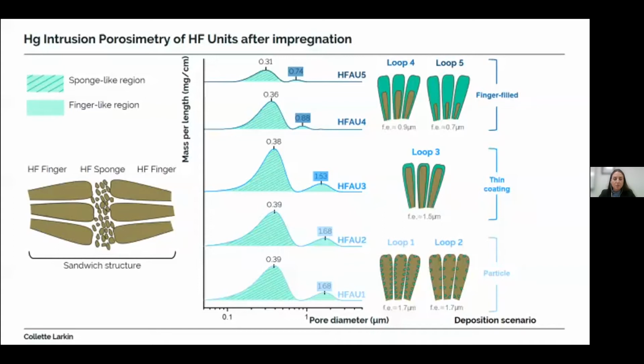And the finger fill deposition scenario effectively builds upon the thin coating scenario, such that once the inner surface area was completely coated, applying additional impregnation loops resulted in calcium oxide depositing onto the existing calcium oxide layer. And so overall, we can see that as expected, as you increase the number of impregnation loops of calcium oxide into the hollow fibre adsorption unit, you are going to increase the saturation level and fill the fingers.